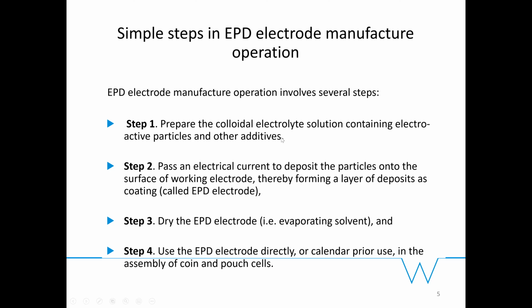And after the electrodes are prepared, the drying step is usually quite reasonably fast compared to if you're doing a classical slurry cast method of using NMP to deposit active materials onto an aluminum foil to prepare either lithium-ion battery electrodes or supercapacitors. They require quite a long time to dry the NMP, so it's quite an energy-intensive process. Whereas in this case, the solvents for EPD that we use, like alcohol or acetone, dry off very fast, so it's less energy-intensive.